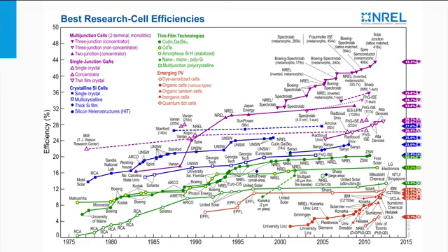The blue lines and dots represent crystalline silicon technology based on monocrystalline and multicrystalline silicon. The record efficiency ranges from 20 up to 25% under standard one-sun illumination conditions, and 27% can be achieved under 92 suns illumination.